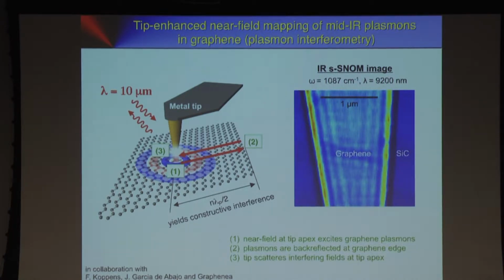But how do we image them? Because they just propagate away. We image them by scanning close to a defect or the edge here. These waves exist only inside the graphene, but not outside. So if we scan close to here, the waves will be back reflected, giving rise to a standing wave pattern, to interference phenomena. And so we imaged here a graphene sheet that was epitaxially grown on silicon carbide, and we see indeed these fringes that are parallel to the edge. And these fringes are nothing else than the standing wave pattern. And the distance between two fringes is half the plasmon wavelength, like in a Fabry-Perot interferometer-like experiment.